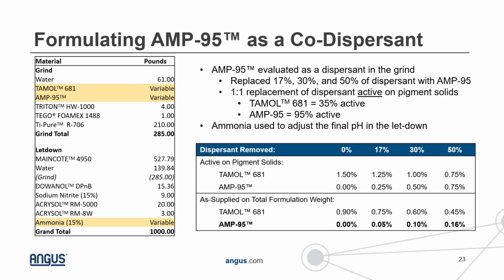Most people aren't used to thinking about using AMP95 in terms of an active on pigment solids, so we can convert this to an as supplied amount on total formulation weight. In this case, we're essentially looking at 0, 0.05, 0.1, and 0.16% weight of AMP95 on total formulation weight. This is how we'll refer to these different formulations in the next couple of slides. But what's also important is that we're only evaluating AMP as a codispersant. To hit our pH target, we still used ammonia. When you use AMP, it will have an effect on the pH, but when we made our final pH adjustment, we're just using ammonia in the letdown.